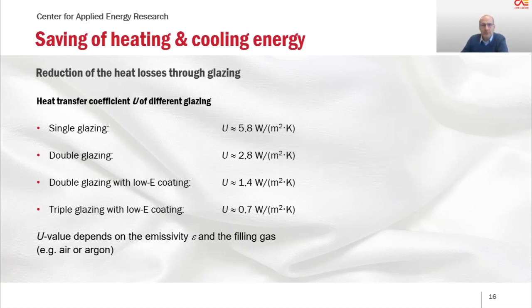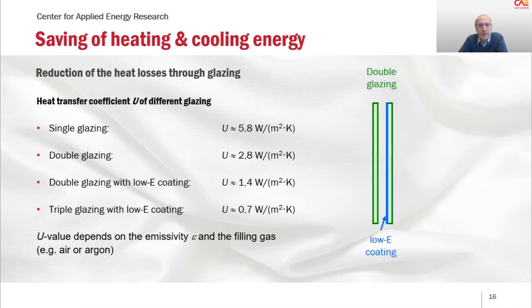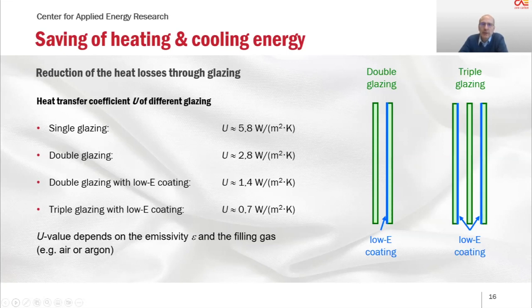And by adding, next, please, by adding a low E coating on the glass sheet, you can reduce or halve the U value again. And finally, you can get to the triple glazing. So the next slide, please. And for the triple glazing, you have 2 low E coatings. And again, you can halve the U value by these low E coatings and by the additional glass sheet. That means by providing transparent low E coatings in this case, the heat transfer can be significantly reduced, and therefore the thermal insulation can be significantly increased. Of course, the exact value not only depends on the emissivity, but also on the filling gas, like argon or air, for example. And the same can be done for wall constructions, especially for external walls.